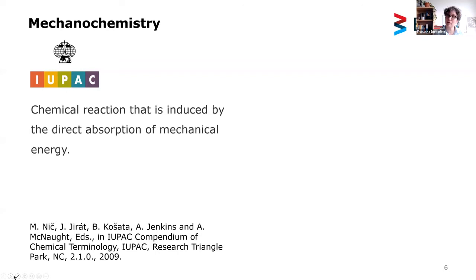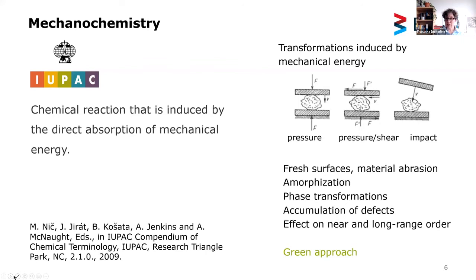But nevertheless, it's a first impression. And here on the right, you can see what we can actually do when we introduce transformation using mechanical energy. We have pressure and shear, and the combination of these works together, and we can then obtain fresh surfaces. Of course, we can abrade material. We also encounter amorphization and, of course, phase transformation. Throughout milling, defects get accumulated in the solids, and then we can see real changes in the near and long range order. What made mechanochemistry especially famous in the last, let's say, 15 to 20 years is the green chemistry aspect. So it's really a green method. It can live without any solvent or only catalytic amounts of solvent, and that makes it very interesting, especially now for industrial chemistry.